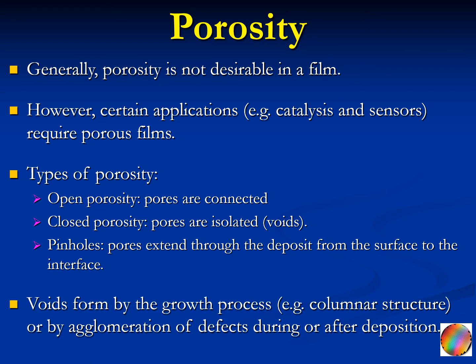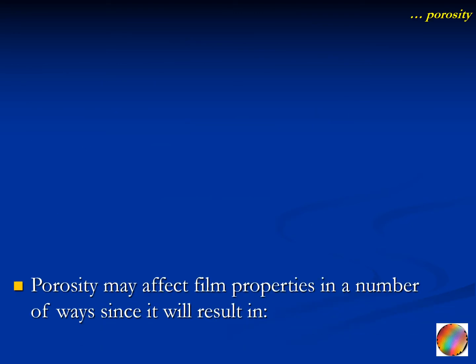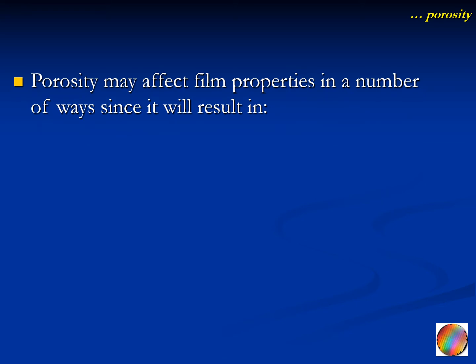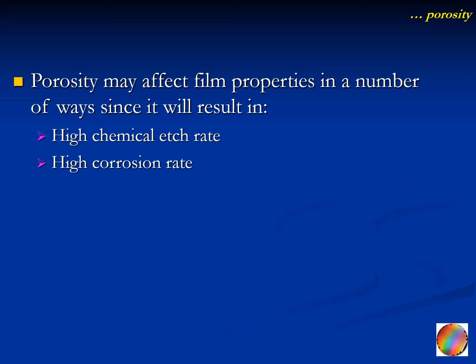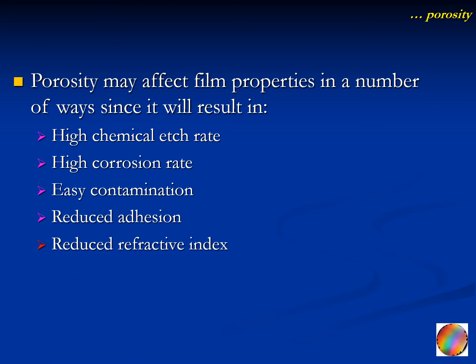Voids form by the growth process, like columnar structure, or by agglomeration of defects during or after deposition. Porosity may affect film properties in a number of ways, since it will result in high chemical etch rate, high corrosion rate, easy contamination, reduced adhesion, and reduced refractive index.